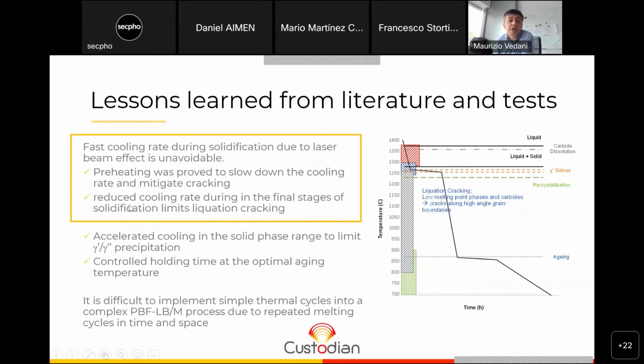So, what can we do? In theory, the ideal thermal cycles that we can design in order to limit or mitigate those defects can be drawn from some considerations. First of all, I need to say that fast cooling rates cannot be avoided in a laser beam process because of the intrinsic power density of the laser. Quite a fast cooling rate is there.